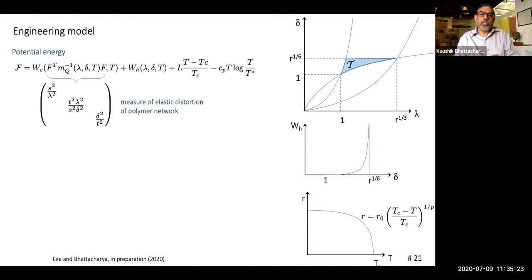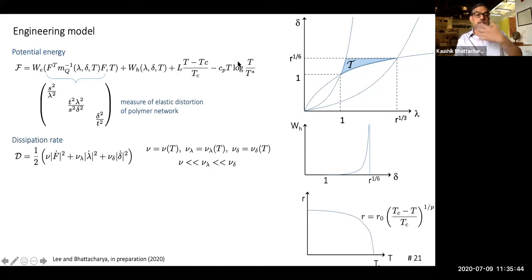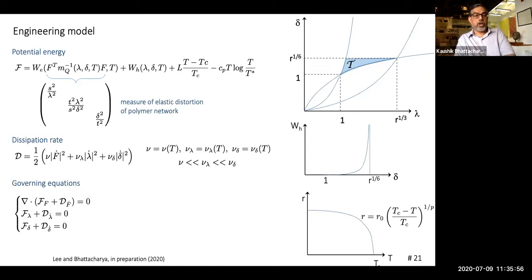And what you find is you can describe this with 2 parameters, which we'll call lambda and delta. This is basically the elastic distortion of the matrix. This is the behavior of some kind of internal stored energy in the microstructure. This is some latent heat because of the phase transition, and this is specific heat. You also need some evolution, so you have some dissipation, and you describe some viscous behavior using a dissipation rate, and we just use basically linear kinetics here. So these are your governing equations.